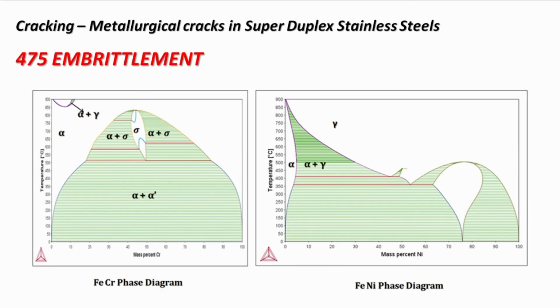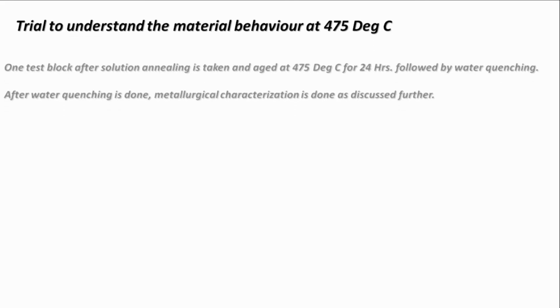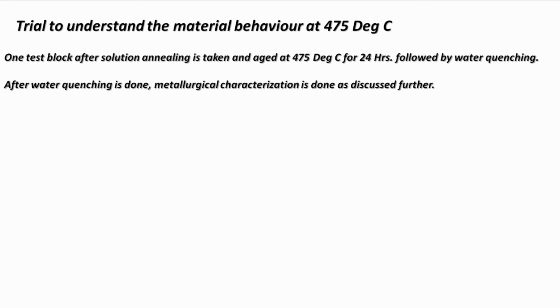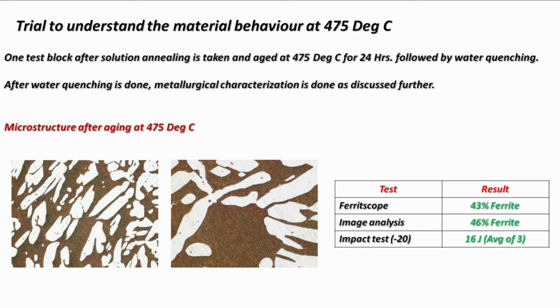So when my material is further heated above 350 degrees Celsius, what happens? This metastable alpha phase starts transforming into its stable phases of alpha and alpha dash. To understand this, first we took one of the test blocks and heat treated it at 475 degrees Celsius for 24 hours, and some metallurgical characterizations were done.